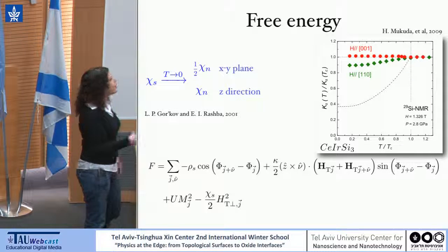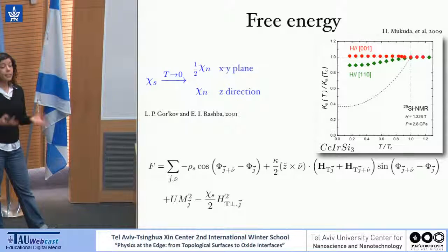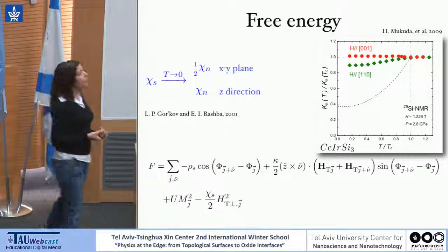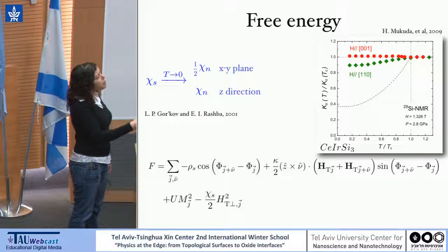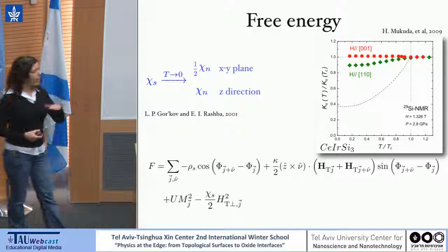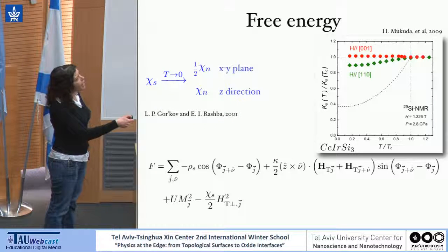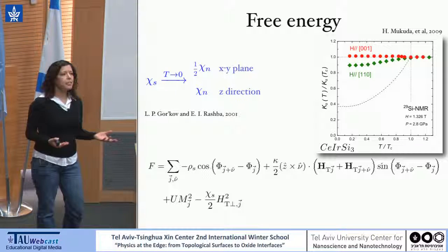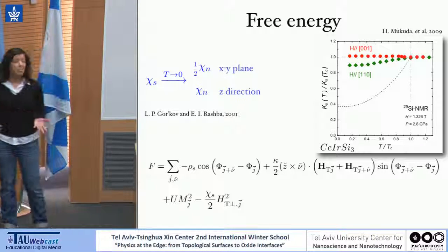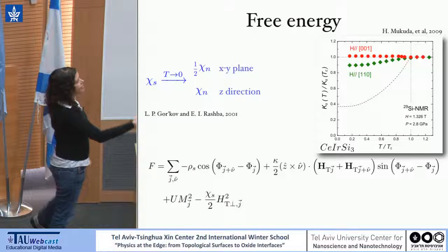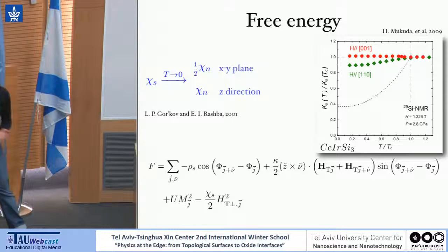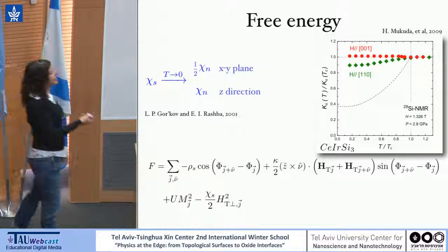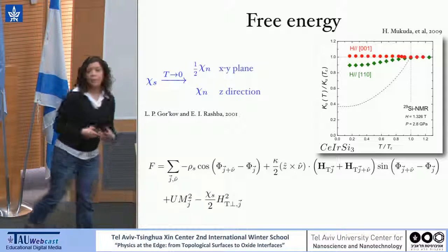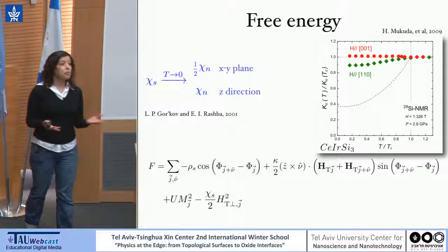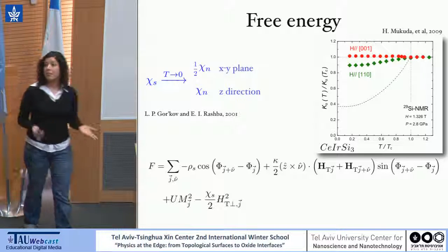For example, in this material, cerium iridium silicon, which is known to be a Rashba type of spin-orbit coupling system, they were looking at the Knight shift, or the spin susceptibility, in two different directions, along the c-axis and in plane. And they were looking at how it changes. Going below TC, you can see it more or less stays as it is in the normal state of the system. And that is because of the spin-orbit coupling. That is very important in our system, because otherwise spin susceptibility would go to 0 and magnetic fluctuations could not do much. They can destroy the phase simply, but not more than that.